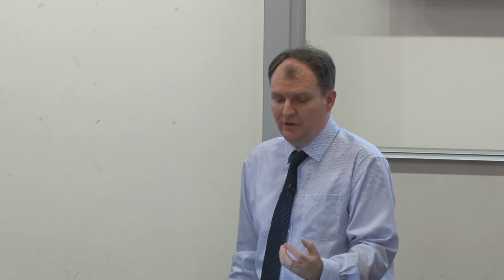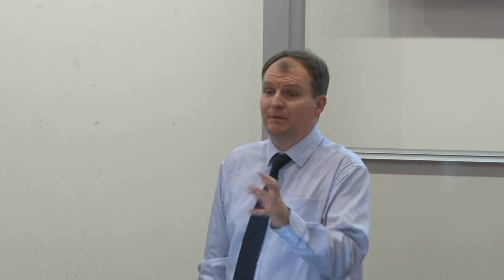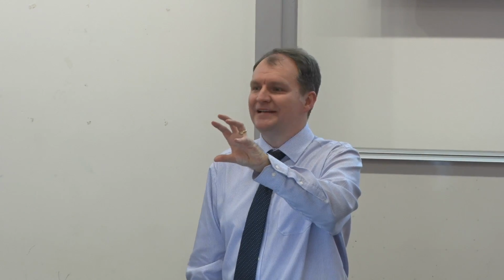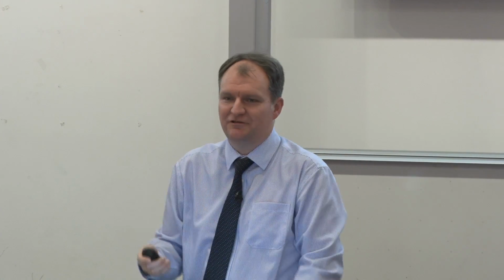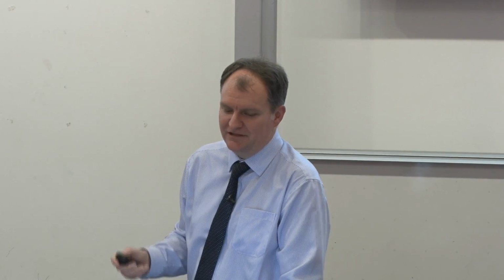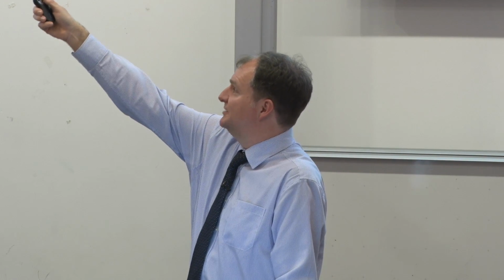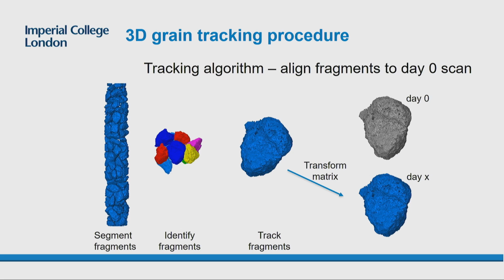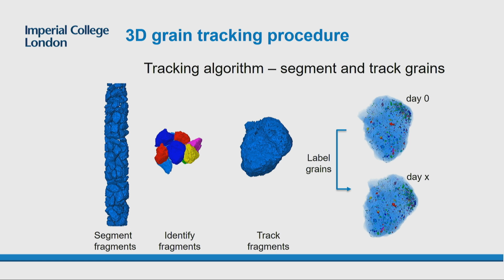But once we've got it, we could then track the individual fragments, and that was needed because as the leaching happens, the rocks settle, they move, etc., so they're not in exactly the same point. And so we need to transform it from what it looked like in its new state to the same one as the original day. And then we could, from that, identify every mineral grain in it and identify the same mineral grain in the first time and what it was like in the later time. So you could tell the change in size of every mineral grain. And this had to be a quick algorithm because in this particular set, we tracked 1.2 million individual grains. So you can produce giant data sets doing this.